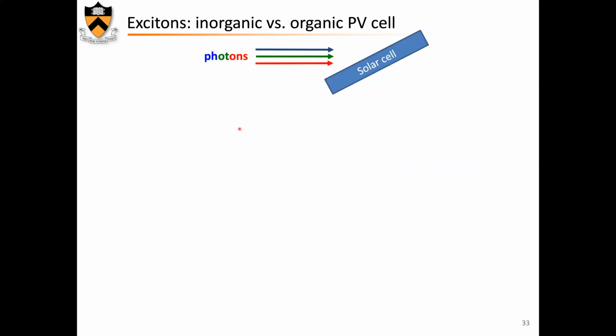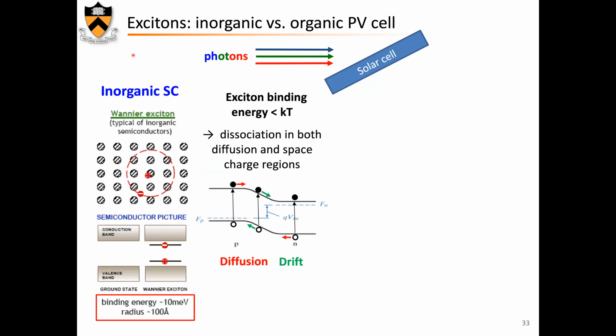So what is the main problem with organic solar cells? If we go back to the inorganic semiconductor, you absorb light, you create an exciton, and this exciton is typically a Wannier type exciton, large radius exciton, in a material that has a relatively large dielectric constant. The binding energy of the exciton is small, 10 millielectronvolts or so. The radius is large.